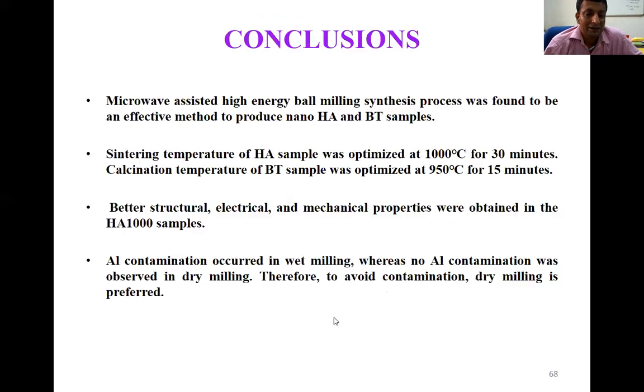So this is the synthesis. We are using microwave assisted high energy ball milling synthesis, and we have synthesized hydroxyapatite and barium titanate. We are obtaining better properties at 1000 degrees Celsius. There was an issue with this impurity that we got rid of by what we call dry milling.